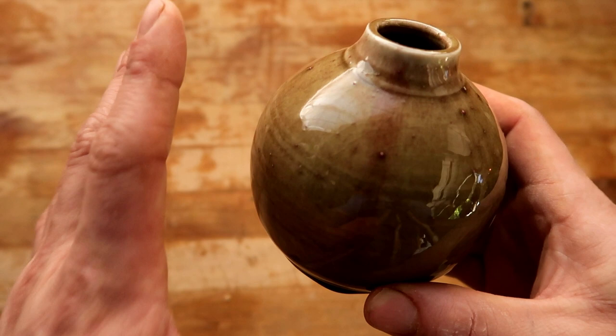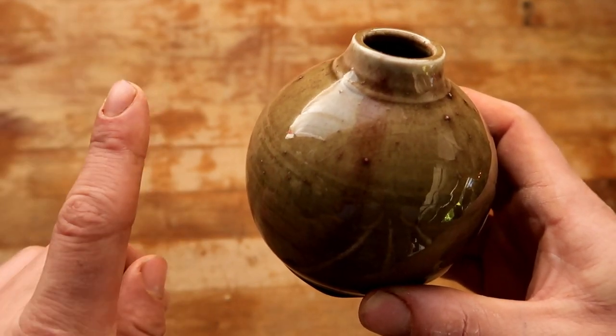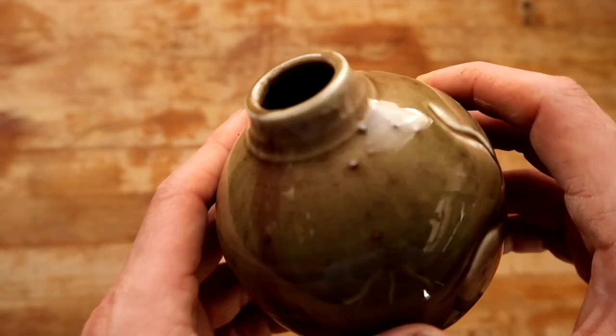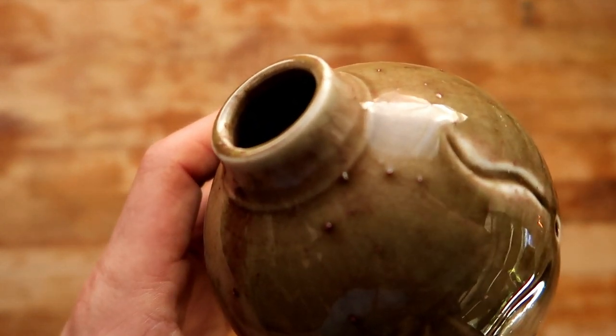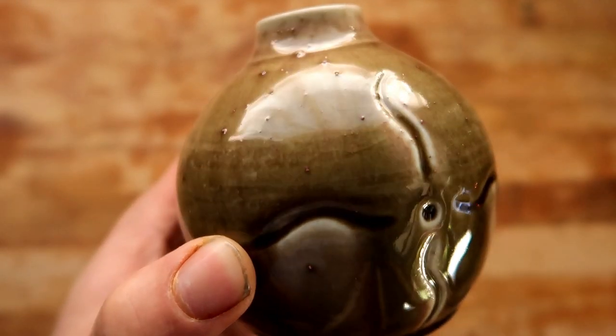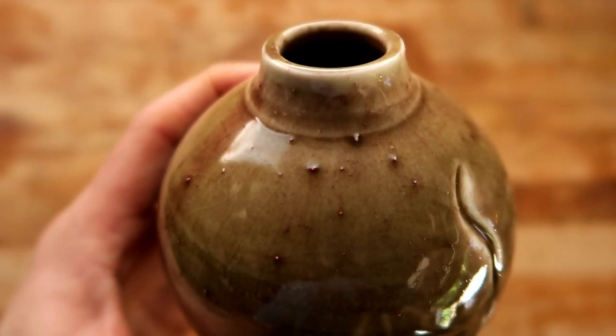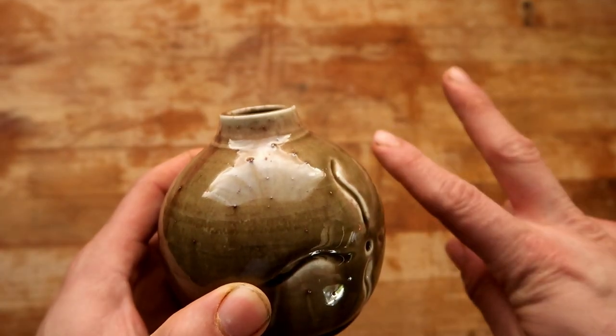So this is purposefully a bad product right here, but there's two things I noticed right out the gate. You probably noticed them too. Number one, these big dots here that are majorly unsieved are the things that are mostly turning red, which makes me think they are the thing that make the red. Which also makes me think this is why this didn't get almost any red, is because the chemical that turns red is all left clumpy instead of suspending in the rest of the glaze in the water like it should.